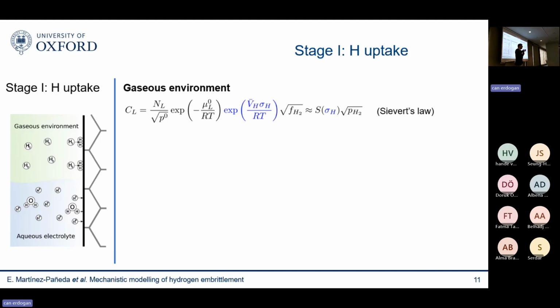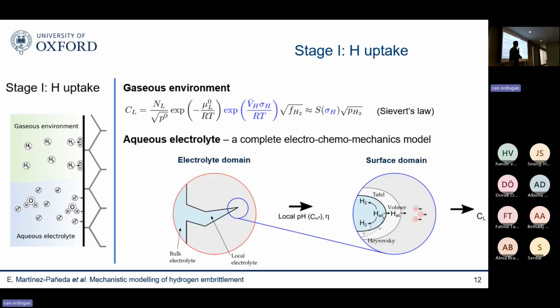Whenever you're doing a permeation experiment, you're going to measure a stress-free solubility, but what you care about is how much hydrogen is coming in when you have a pressure vessel with a crack. And when you have a pressure vessel with a crack, you have an exponential term with a hydrostatic stress. And the hydrostatic stress, of course, is going to be very large near cracks. So the mechanics contribution is important and should not be ignored. But anyway, that's good news.